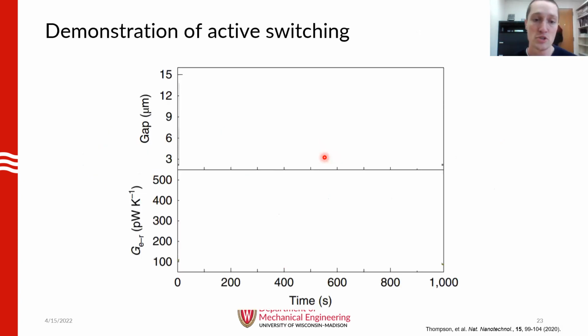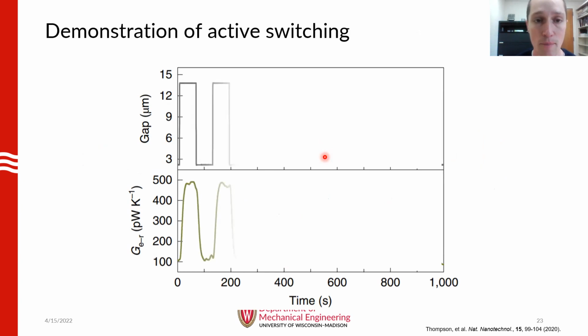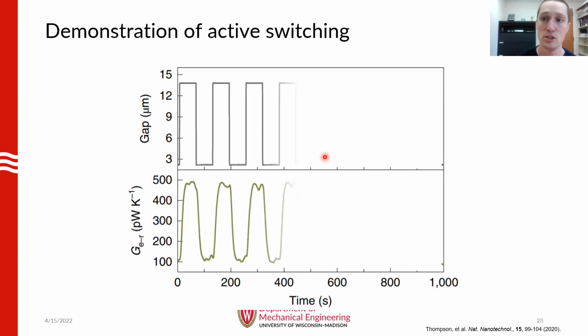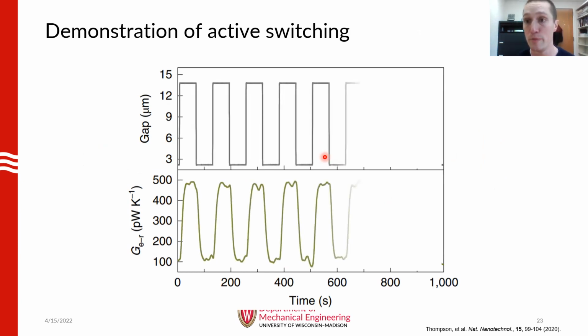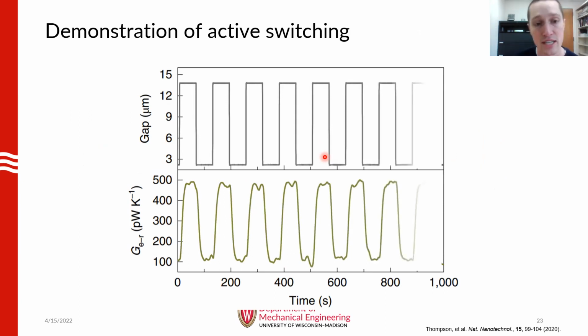On this slide, I also want to demonstrate that we could achieve active switching using this approach. In the top panel, you can see a time trace of that vertical offset between our emitter and receiver and the bottom gold modulator. Here the gap was modulated from 14 to around 2 micron with a period of 2 minutes. And on the bottom panel, you can see a time trace of the radiative conductance, which here is switched on and off with a switching ratio of around 5.